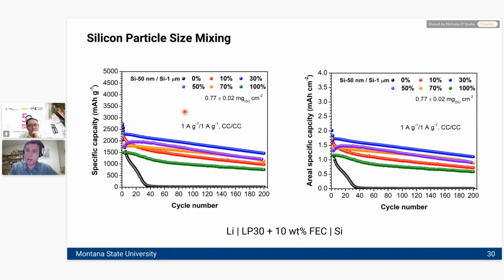Even the same supplier, nominally the same material, did not have the same performance properties in different rounds of buying it. And so my postdoc decided he wasn't going to wait around, and he was too impatient to figure that problem out. He decided to just start by mixing different precursors in the lab that we already had. In this case, he's mixing that one micron sized microparticle silicon, the one that really doesn't do well, together with this 50 nanometer precursor that we had sitting around in the lab.